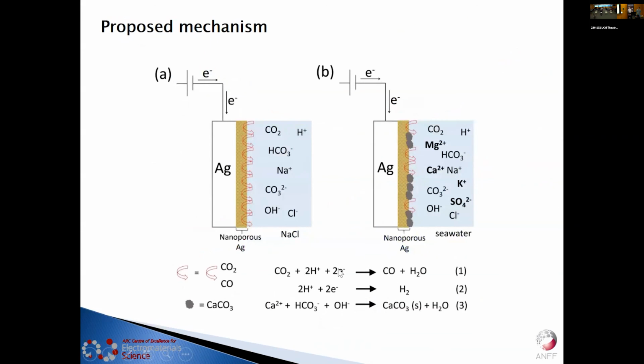So we have two processes happening. The first one is CO2 reduction to CO, in this case using silver, and then also the competition of proton reduction to hydrogen. And interestingly, we can capture the CO2 in a carbonate form to form calcium carbonate. So we have a reduction and storage-capture approach.